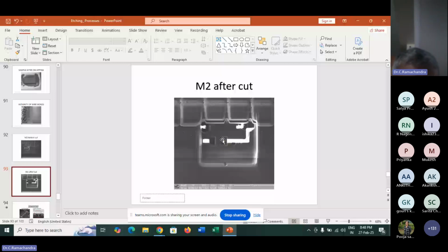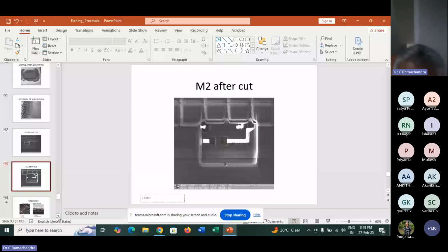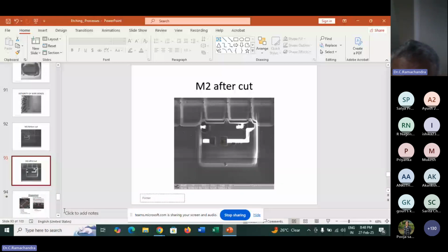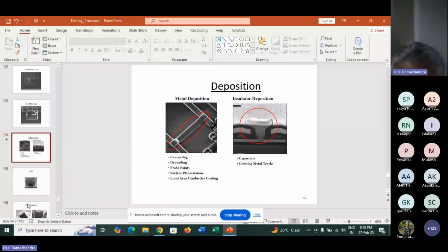Similarly, it is not only etching, this can be used even for deposition. Suppose some metal is missing, a connection is missing, the device is not working, and we come to know after the device is fabricated. So what we do is take the device, and see, we deposited the material. Here the connection was missing from here to here, we deposited, and after deposition, we test it again. Because we have to maintain the integrity. Then if it works, that is the feedback.